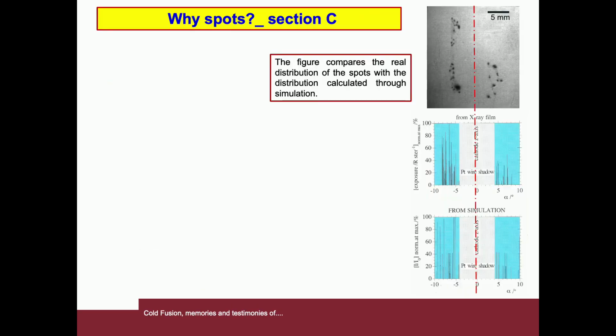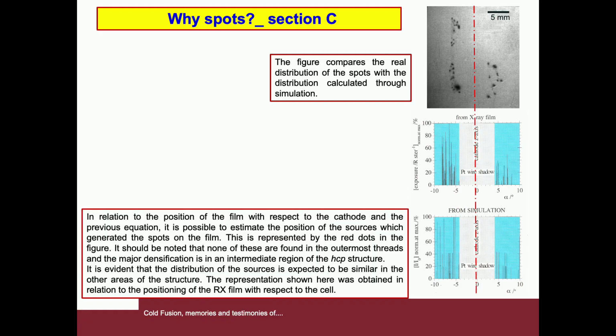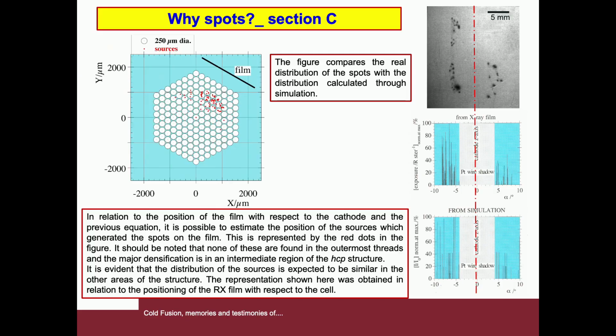Why spots? Section C. The figure compares the real distribution of the spots with the distribution calculated through the simulation. As we see, there is enough correlation between the real and the calculated situation. From the position of the film with respect to the cathode and the previous equation, it's possible to estimate the position of the sources which generated the spots on the film. This is represented by the red dots in the figure.